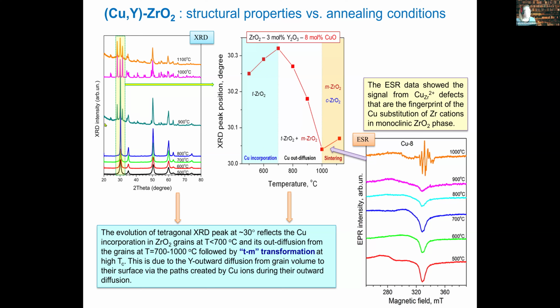As you can see from the left image, it shows the evolution of X-ray diffraction taken from the powders doped with yttrium and copper, about 3 mol% of yttrium and 8 mol% of copper oxide. You can see that until 800 degrees Celsius the spectra do not vary, so we know that our materials were stable with tetragonal structure, and annealing at 900 degrees Celsius and higher resulted in complete transformation of tetragonal structure to monoclinic. The X-ray diffraction peak at about 30 degrees usually shows the variation of tetragonal to monoclinic phase and vice versa.